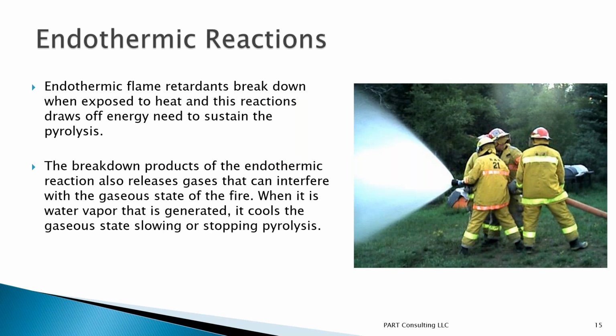Endothermic flame retardants break down when exposed to the heat, and the reactions, of course, draw off the energy needed to sustain the fire. Basically, it's a fire hose. It basically releases water, and it enters into the gaseous phase, and that cools the fire state, and with enough of the additive in there, it can actually stop the fire on its own.